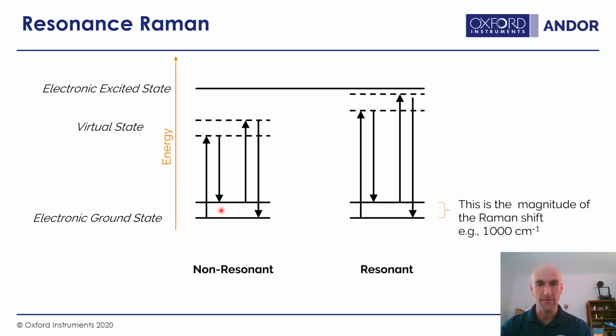So if we had multiple degrees of freedom, we'd have multiples of these that would be kind of orthogonal to each other. And what happens in non-resonant Raman is that we have some far away or possibly non-existent electronic excited state that we don't worry about. All we care about is the electronic ground state. We scatter, where we have a photon come in with some energy, goes up to a virtual state, and immediately comes back down to a vibrationally excited ground state. So this would be our Stokes shift, because you can see this arrow in energy, that's the photon in, is a bit longer, a bit higher in terms of energy than the photon that comes out. So this is our Stokes.